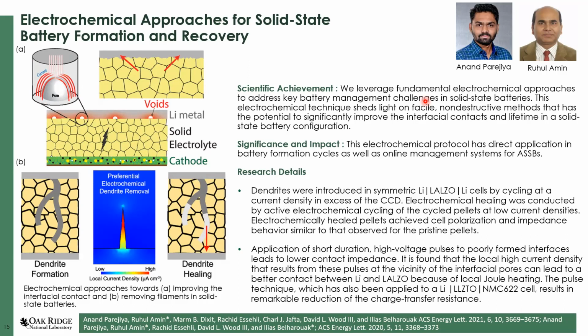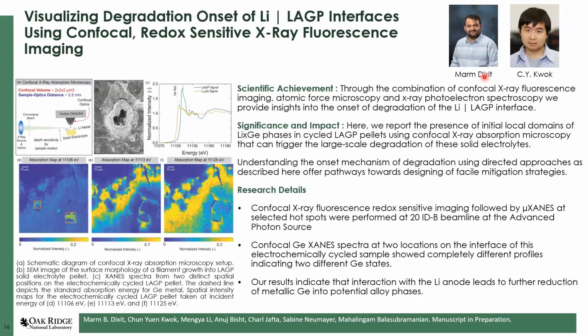So to understand this and to see if there are mitigation strategies, Ruhul Amin and a student from UTK, Anand, worked on it. And they have come up with an electrochemical way by which you can heal dendrites that go into the solid electrolyte. By passing very small currents using a very particular electrochemical protocol, they have figured out ways by which you can make these lithium dendrites which have penetrated the solid electrolyte disappear. So if this can become a standard protocol in real batteries, one can periodically check to see if you have dendrites and try to wipe them out with a simple electrochemical protocol.